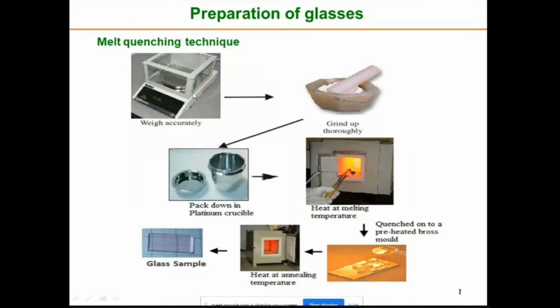You just take the raw material, weigh them and grind them, and you melt them in a platinum crucible, depending upon how much impurity you are going to minimize. It depends upon the glass material, and in order to minimize the impurities while melting, you can use a platinum crucible, or silica crucible, or alumina crucible. Even sometimes they use a porcelain crucible. They melt it and they pour it and again anneal it, and this is the glass that you are getting.